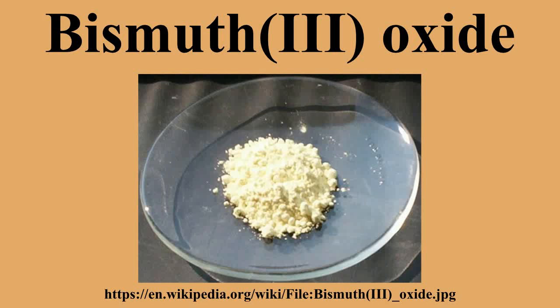Gamma bismuth trioxide has a structure related to that of Bi12SiO20, where a fraction of the Bi atoms occupy the position occupied by Si(IV), and may be written as Bi12(Bi0.8O19.2). Delta bismuth trioxide has a defective fluorite-type crystal structure in which 2 of the 8 oxygen sites in the unit cell are vacant. Epsilon bismuth trioxide has a structure related to the alpha and beta phases, but as the structure is fully ordered, it is an ionic insulator.